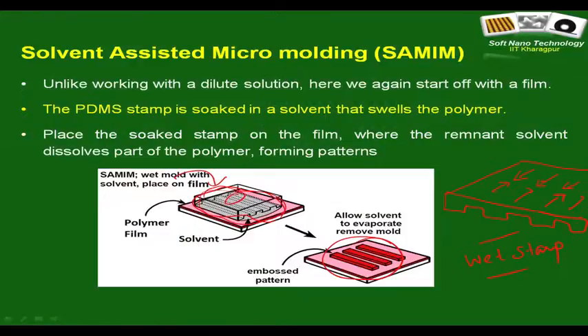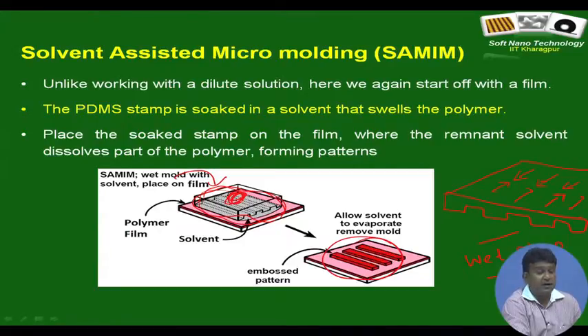Over the central areas, how does the solvent evaporate away after patterning? The rate of evaporation from the peripheral zone will be much faster as compared to the core area, and if the core area contains solvent and you withdraw the stamp, what in fact happens is you are leaving behind a patterned polymer layer whose viscosity is too low, which is too fluidic. So, because of surface tension issues, Laplace pressure, it tends to flatten out.